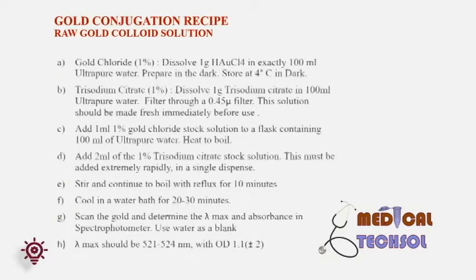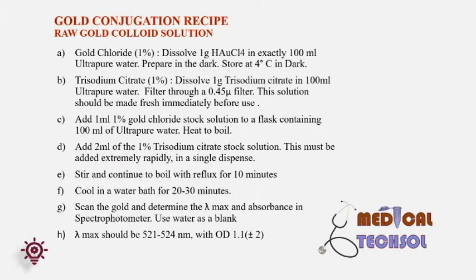Here is a typical formulation of the gold conjugate recipe. 1. Raw gold colloid solution preparation — 1% gold chloride: dissolve 1 gram of tetrachloroauric acid (HAuCl4) in exactly 100 ml of ultrapure water in a dark room, as gold chloride is light sensitive. Store this solution at 4°C covered with opaque material. 1% trisodium citrate: dissolve 1 gram of trisodium citrate in 100 ml of ultrapure water and filter through a 0.45 micron filter. This solution should be made freshly.